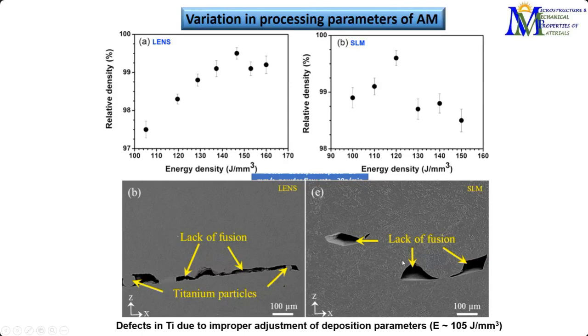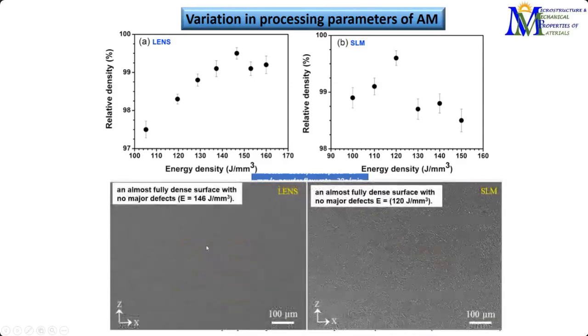So we have to ensure that we use the right energy density, changing the processing parameters accordingly. Whereas if we use an energy density of 146 for LENS versus 120 for SLM, we end up having a completely compact structure with no such defects. So we can see that SLM requires lower energy, so should be more cost effective.